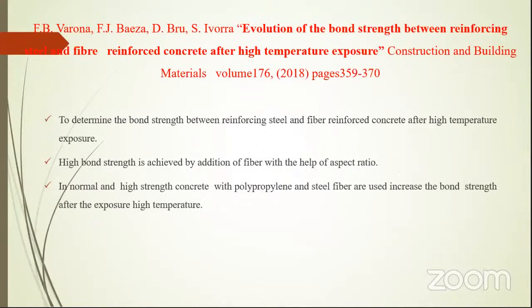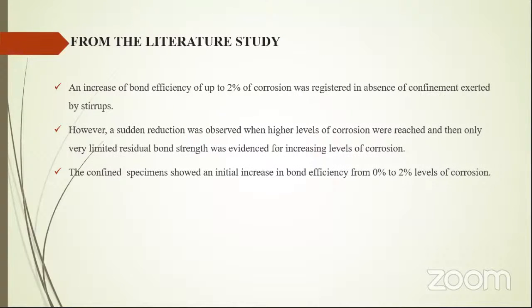The next paper is about evaluation of the bond strength between reinforcing steel and fiber reinforced concrete after high temperature exposure, to determine the bond strength between reinforcing steel and fiber reinforced concrete after high temperature exposure. High bond strength is achieved by addition of fiber with the help of aspect ratio. In normal and high strength concrete, polypropylene and steel fiber are used to increase the bond strength after the high temperature.